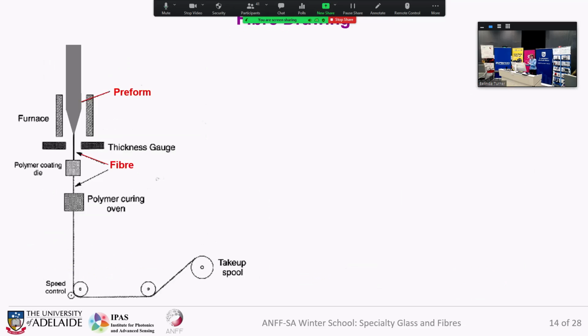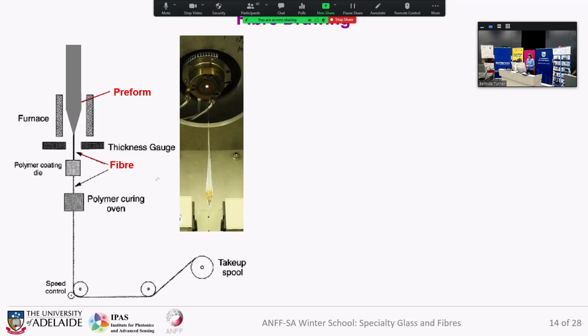So this was all about preform fabrication. Now I'm moving on to the fiber drawing. There you see the preform inside a furnace, inside a hot zone. Only a short part of the preform is heated up. If the heat is going on for a few minutes, then the glass softens, gravity forms a neck down, and a drop is coming down, as is shown in this photograph.